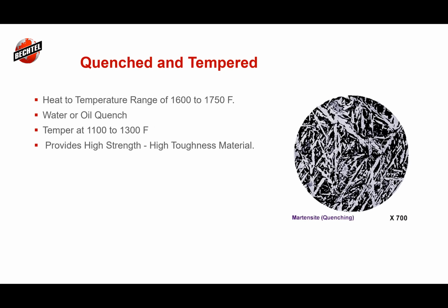So the T1s now have, not only all of the alloying elements in them, but they have this temper. And when we temper the material, you have to be really cautious with the quenched and tempered materials, that when we go back through and do a post-weld heat treatment, for example, we make sure that we don't allow the material to get too warm where it erases the effects of the temper. And this is why for some of the 514 materials, most of the time, they would recommend as a general rule that there's no post-weld heat treat on the quenched and tempered 514.